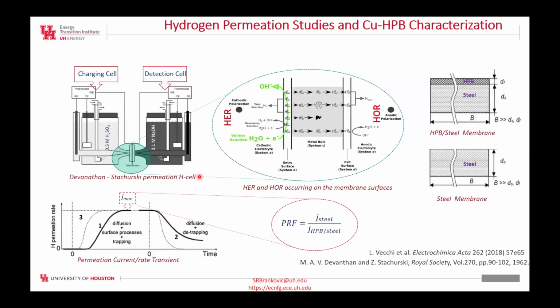Nevertheless, the final word about the quality of the barrier is done by real permeation test in, as I mentioned, the electrochemical permeation cell, where in the charging cell we produce hydrogen by hydrogen evolution reaction on the surface of our steel or double layer coupon, and this hydrogen evolution also causes hydrogen to permeate in the sample and exits the other side of the steel in the detection cell, where we measure the hydrogen oxidation current related to this hydrogen flux. And basically the ratio between these currents measured in a detection cell for the steel sample and steel sample coated with a permeation barrier layer of copper gives you permeation reduction factor.